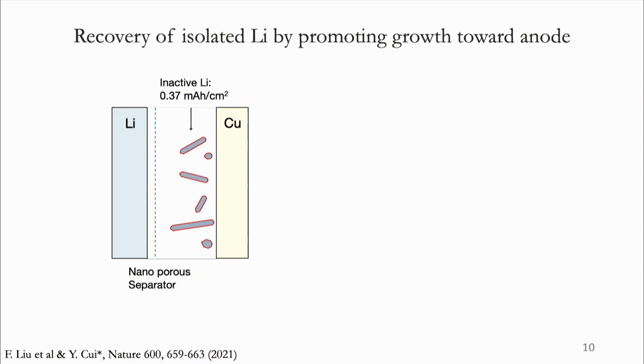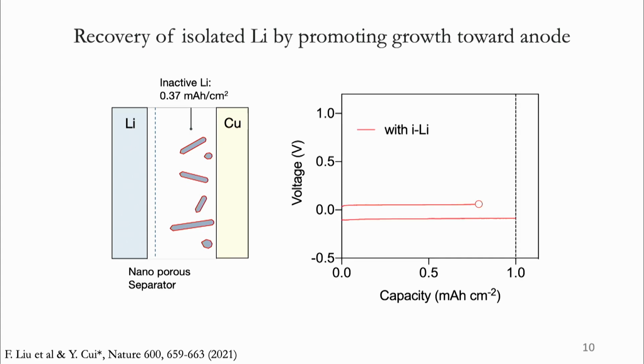This is one of the demonstration experiments that we did with half cells. The half cells are based on copper and lithium to eliminate the influence of the cathode. Basically, the performance that we're looking at is on the copper side. During the first cycle, we want to form a certain amount of dead lithium, or isolated lithium, on the copper electrode. And during the second cycle, we want to see whether we can recover it. During the first cycle, we are forming 0.37 milliamp-hour per square centimeter of isolated lithium on the copper electrode. And during the second cycle, we still want to do deposition, meaning we are charging the battery.